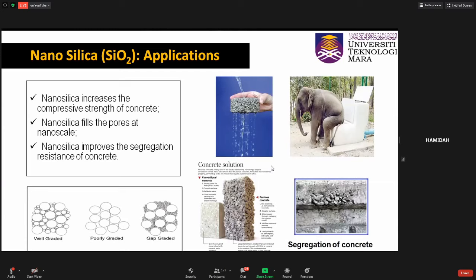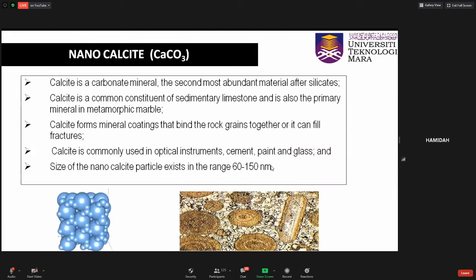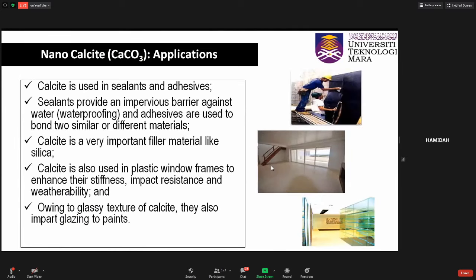Calcite is a common carbonate mineral, the second most abundant after silicates. The size of the nanocalcite particle exists in the range between 60 to 150 nanometers. Nanocalcite is a very important filler material like nanosilica and can be used in sealants and adhesives to improve stiffness, resistance, and weatherability of the resulting composite. Owing to its glassy texture, calcite also imparts glazing to paints.